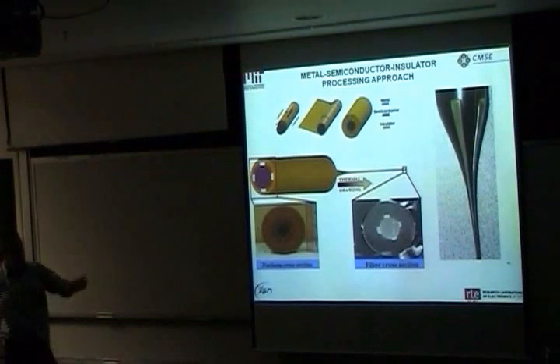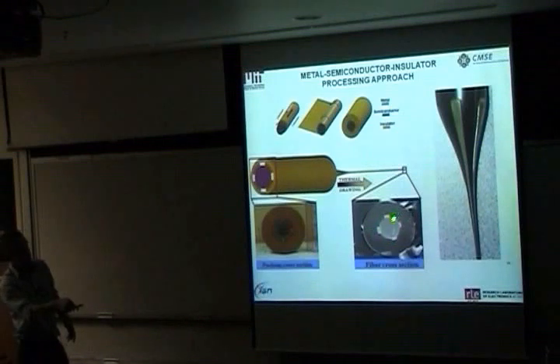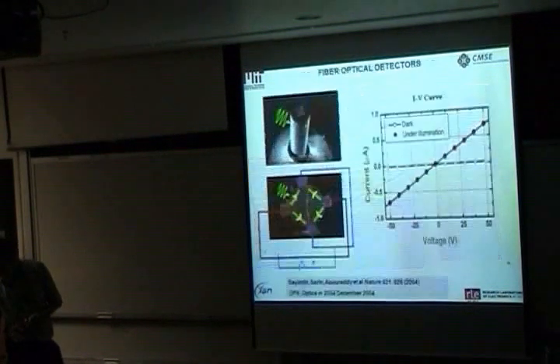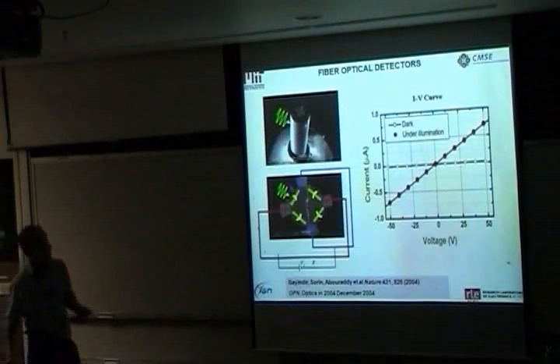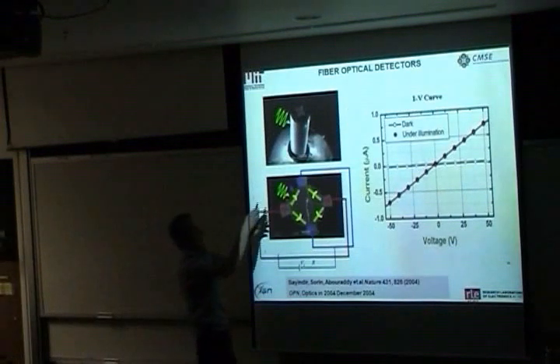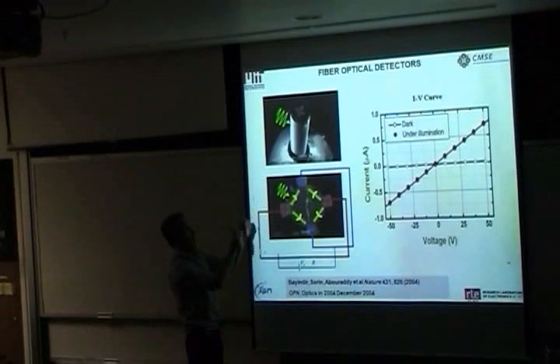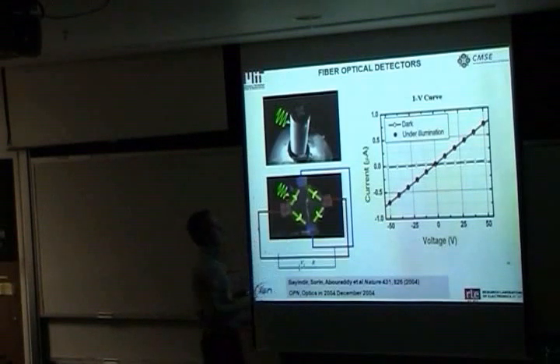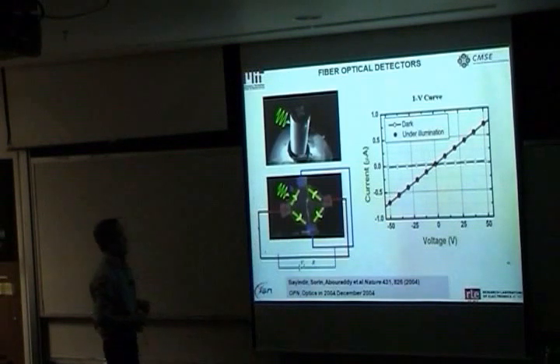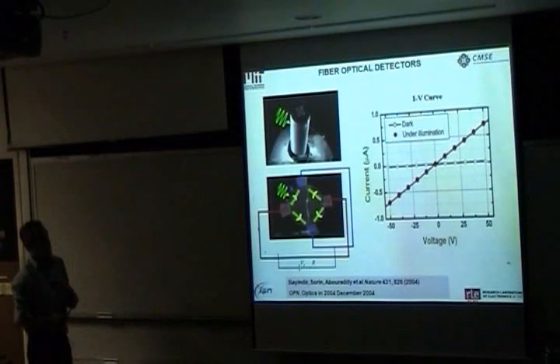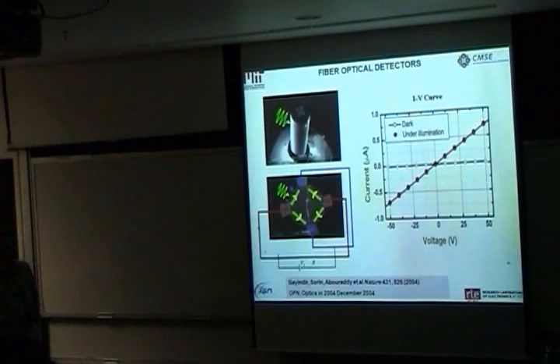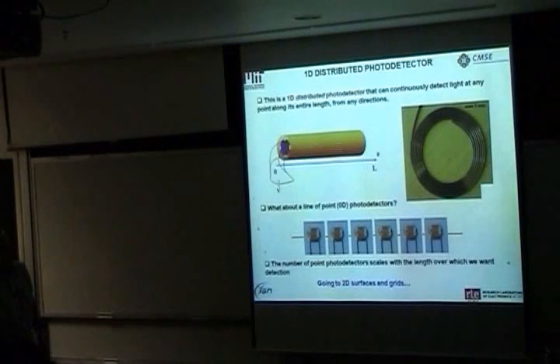And we're able, by doing so, to create fibers that have semiconductor contact with metal and polymers that could be drawn and are very long one-dimensional devices. And when you connect the end of this fiber to a circuit and then illuminate it, basically you get changes in conductivity, photoconductivity. You could detect those changes, and those changes could be used as a simple photoresistor to detect illumination along the entire length of your fiber.